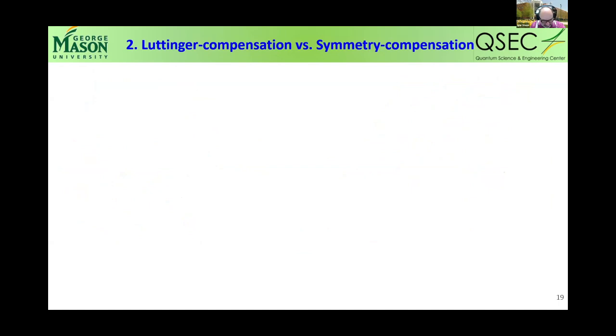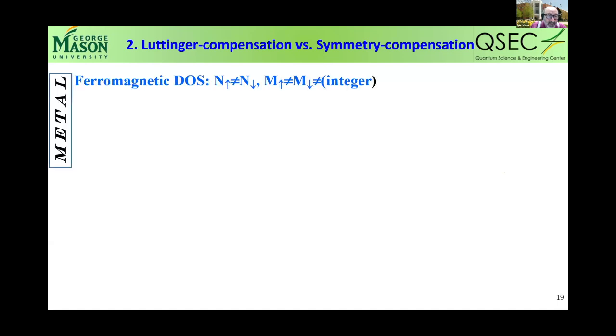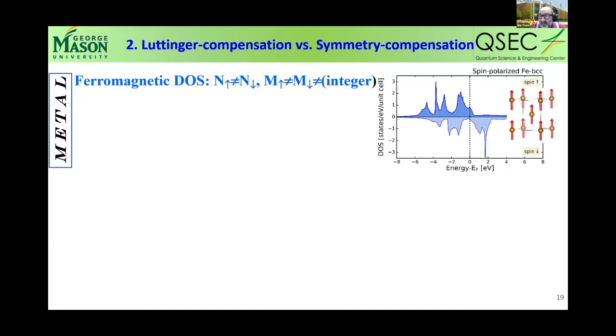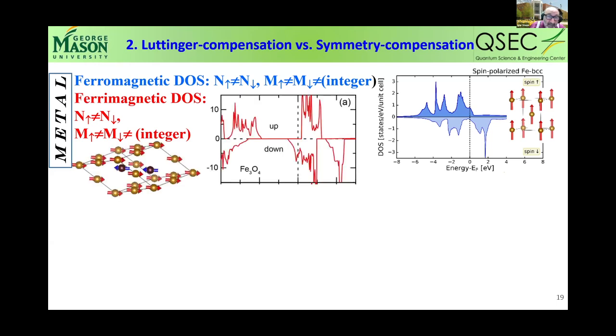And finally, in the last 2-3 minutes, Luttinger compensation versus symmetry compensation. So let's take a standard metal. This is spin-polarized iron in the BCC ferrite phase. There are two different densities of states here for spin up and spin down. They have nothing to do with each other. The net number of spins up and spin down is not the same, and actually can be any number. It doesn't have to be an integer.